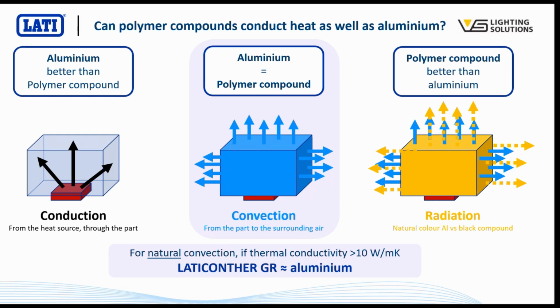So this is a value that we arrived at through extensive testing at LATI, and also independently extensive testing carried out by Vossel-Schwaber as well, to arrive at this kind of 10 watts per meter Kelvin value. So this is the key thing to remember, really. Don't focus on absolute thermal conductivity. As long as we've got a value that's around 10 watts per meter Kelvin or above, then a thermally conductive plastic can dissipate heat just as well as a metal can.